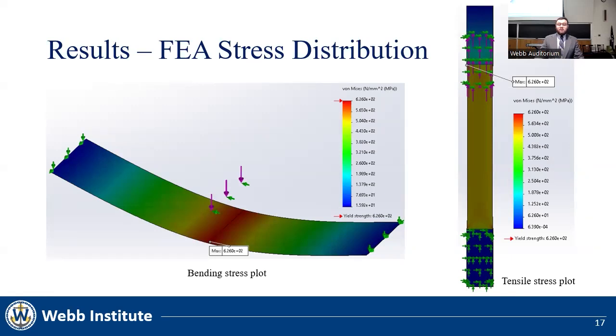Shown here are the bending test stress plot on the left and the tensile test stress plot on the right, in order to see the stress distributions over the specimens. Here, the point of maximum stress for each test can be seen. Another important observation is the necking that occurs in this test, indicating a plastic deformation of the composite.